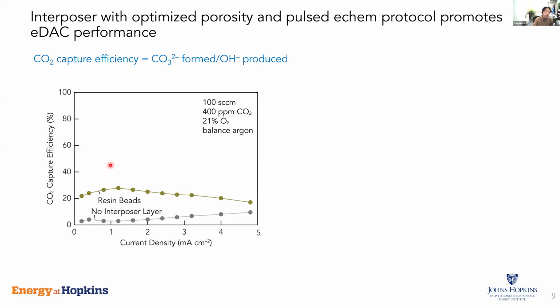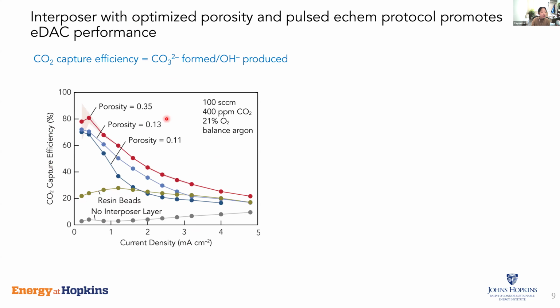So as we introduce only the resin beads, so not the wafer yet, you can see because the resin bead occupies some of the volume to increase the residence time of the hydroxide, you can see a slightly increased CO2 capture efficiency. But once we introduce our wafers with varying porosity, you can see a drastic improvement of capture efficiency, especially at the lower current. And there is a dependence of the performance with respect to the porosity, right? So as we keep increasing porosity to allow more air to come through, the performance gets higher, but there's a limit. So if we further improve the porosity, the performance decayed because we don't have enough anion conductive pathway for the hydroxide to percolate efficiently through the interposer layer.